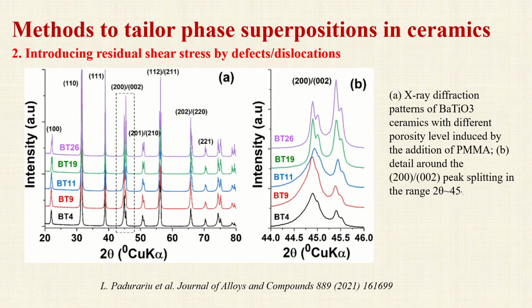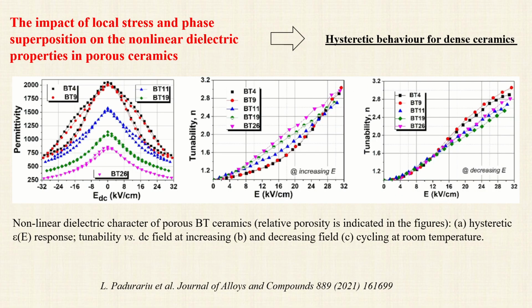In our group, barium titanate powders with local defects and dislocations were used to prepare porous barium titanate ceramics with various porosity levels from 4% to 26%. In these samples, porosity helped release the internal stress, and therefore we obtained samples with predominant orthorhombic phase in dense ceramics and tetragonal phase in porous structures, as shown by XRD analysis. The local stress and phase superpositions had a major impact on the nonlinear dielectric properties.